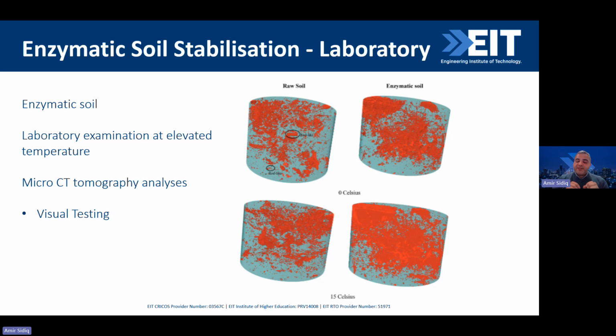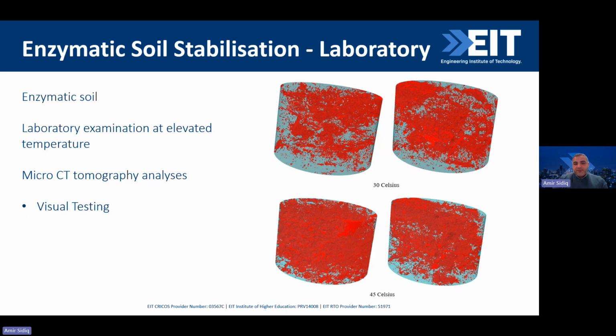Even though it's expansive soil or clay, we need to have this void to be able to equilibrate the material behavior. So here, the void for the raw material is actually low, and for the enzymatic it is slightly higher. But then after 15 degrees, the void for the enzymatic is increasing slightly, and relatively it's also increasing for the raw material. And at 30 Celsius, now the void is starting again to increase for the raw, and then slightly increase for the enzymatic.